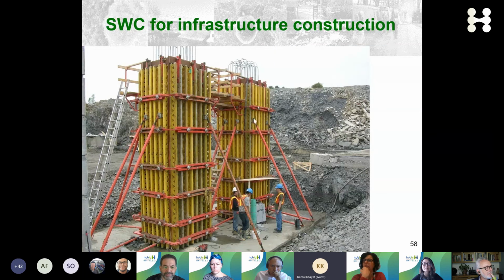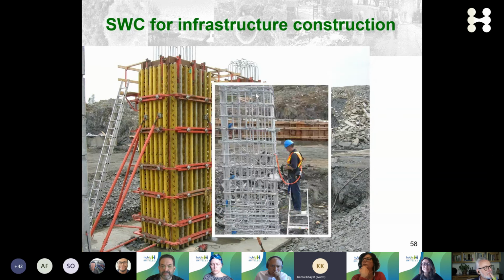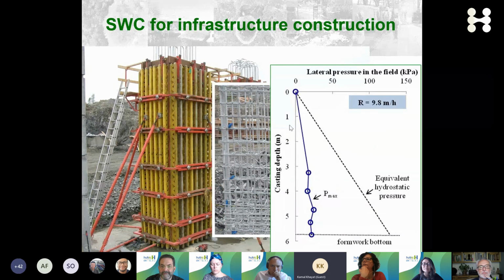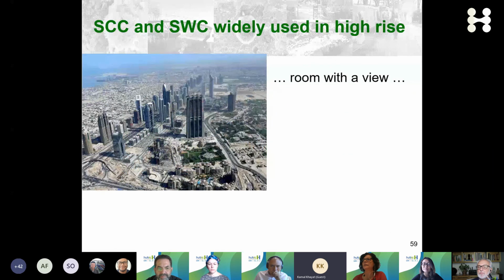It was cast for those elements. You see our technicians, we were interested in form pressure. Form pressure was very, very low, much lower than that of SCC. It was a very robust and cost-effective material that gave very good surface finish and very good performance.